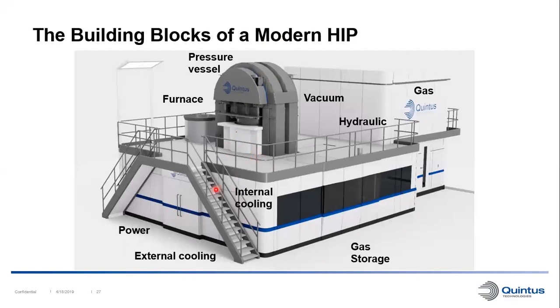And that internal circuit is cooled with an external cooling system. Then we have a gas storage, which contains the argon gas used for the process. And the argon gas goes through a gas module, which will pressurize the gas to generate the high pressure in the process. And this is done with one gas compressor or several gas compressors. There's a hydraulic system as well to create the movement, for example, moving the frame back and forth for opening and closing the system. And also the hydraulic systems are driving the gas compressors. There's a vacuum system, so we can evacuate the air from the system before we start running a cycle.